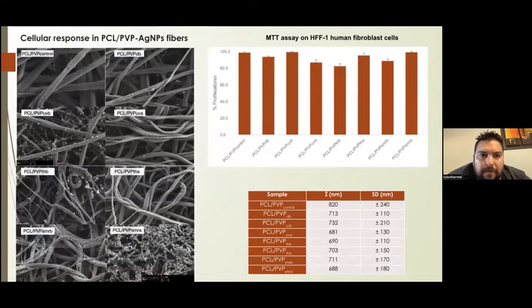So from one of our experiments, we have here polycaprolactone, polyvinyl pyrrolidone fibers loaded with silver nanoparticles. And here I'm showing different kinds of fibers prepared by the 4 different methods that I showed you before. We obtain different fibers with different average diameters, around 700 nanometers. And as you can observe, these fibers don't alter the cellular replication of human fibroblast HFF1.